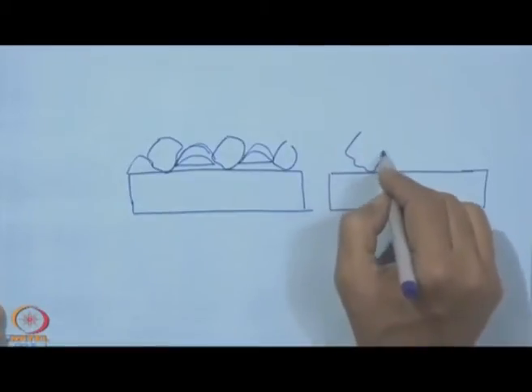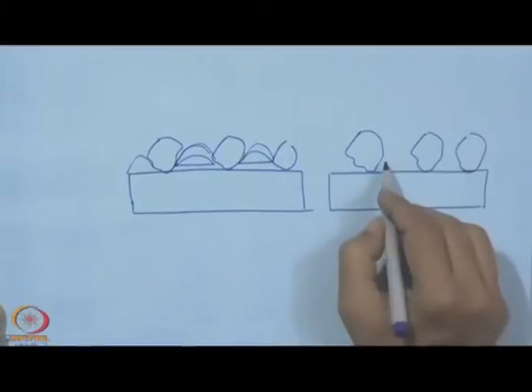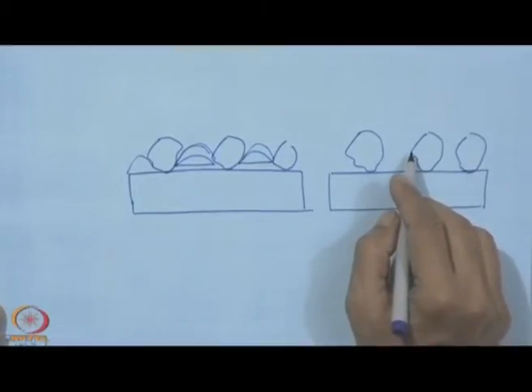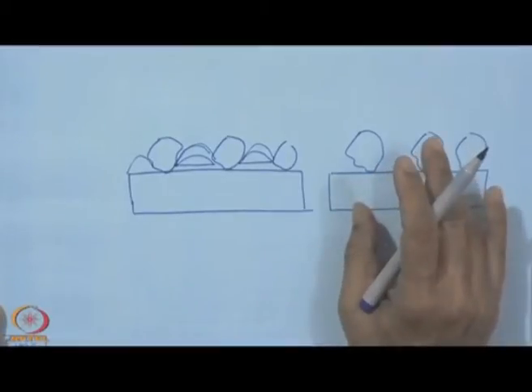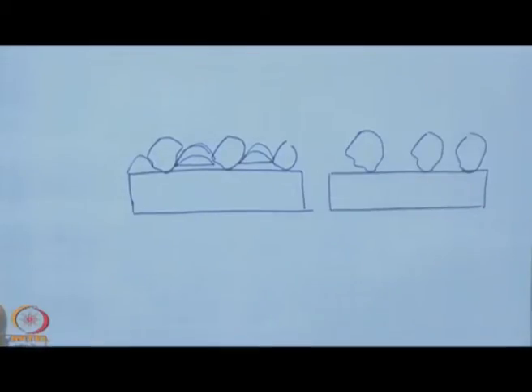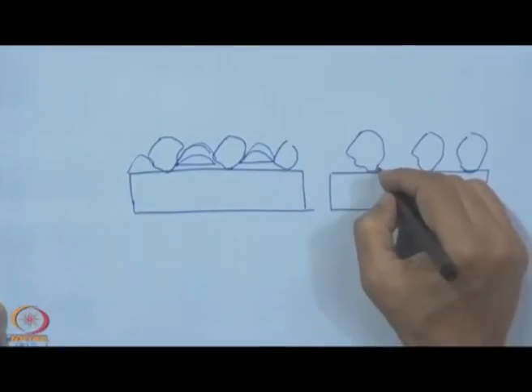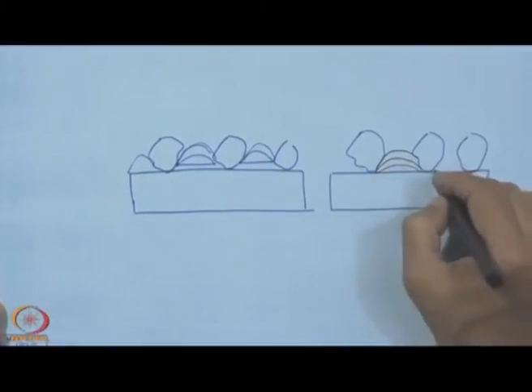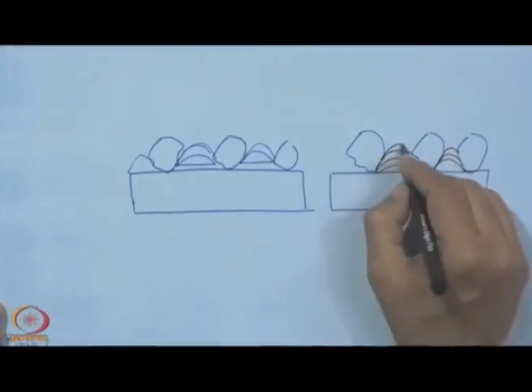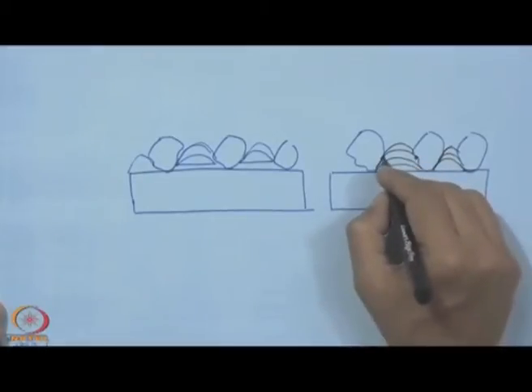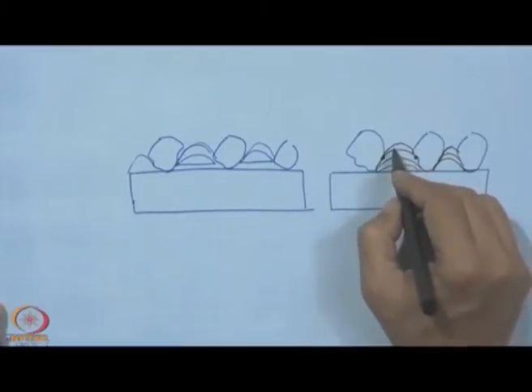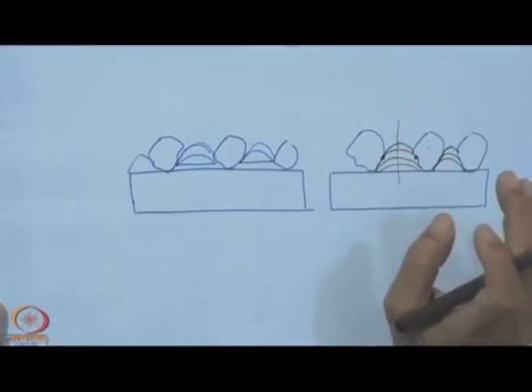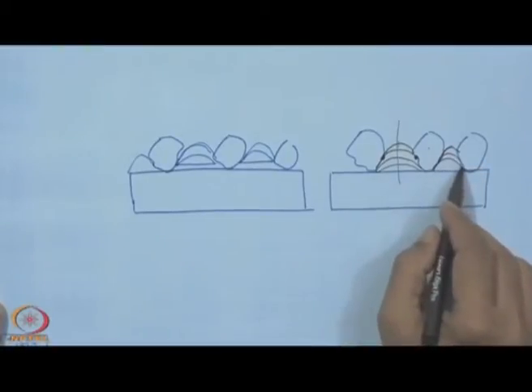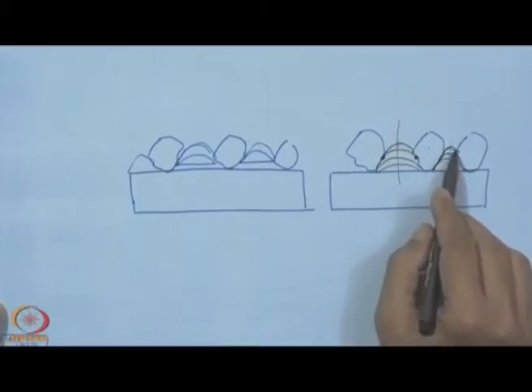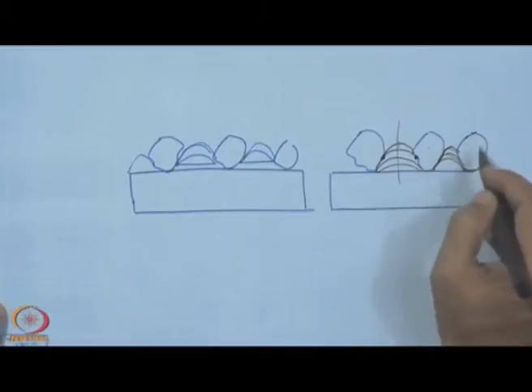This will have a negative influence in that if these are the crystals, our aim is to hold this crystal with adequate bonding and maximum available space. But if the growth of the material is like this, like a nodule formation, then it is not going to serve the purpose, because in this case what is going to happen is that at the root on the side of the crystal you have little metal, and in the space in between the crystals we have a high level of metal, and it is just not going to serve the purpose of grinding. So, this evolution of hydrogen and entrapment of hydrogen should also be properly addressed, how to remove or eliminate this problem.